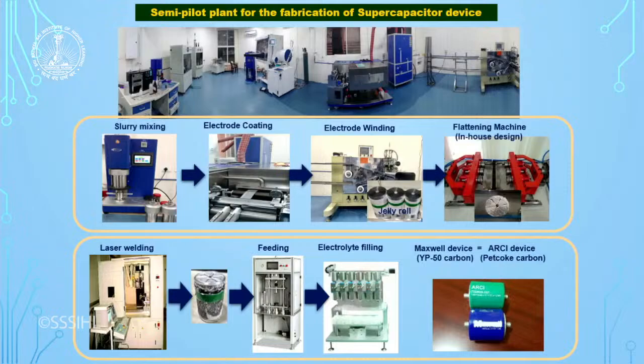So here HPCL has a lot of oil refinery waste that is called pet coke. So this pet coke is a big problem again for all the oil refineries. Again they said, can something be done? So this is again made into activated carbon, and we found that with the jute stick, the yield is only 28%. So with 28% yield, we need a lot of effort to upscale to 10 kilos or 100 kilos. So then we found that this is giving almost 60% yield for the activated carbon, and we further progressed by making the activated carbon material using the waste material from HPCL, and once it gave good results, they have sponsored buying all this pilot level equipment, and we have made these cylindrical cells of supercapacitors and shown that it is working out well.